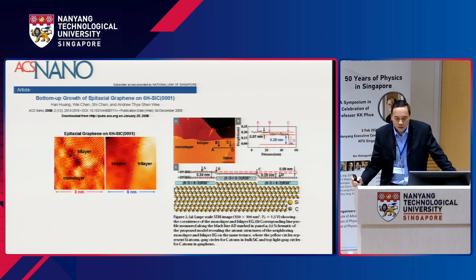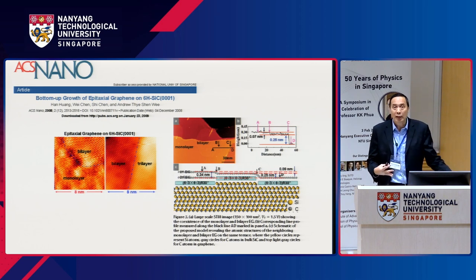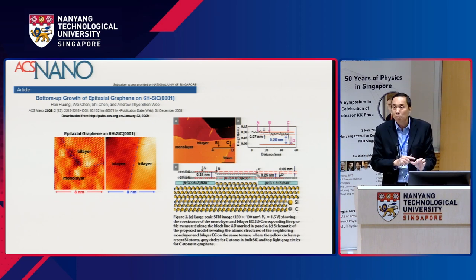So you can actually grow graphene on silicon carbide, which some people have tried to make devices on because silicon carbide is a wide bandgap material. It is still popular with some people, but it is still a fairly minor area of research because of the difficulty in growing large wafer scale size graphene on such a substrate. I mean, we work with STM so we can study very small scale, micron scale or millimeter scale. But the moment you have a wafer size, centimeter scale, that's where the difficulty comes in. You can't get a continuous layer of graphene across it.